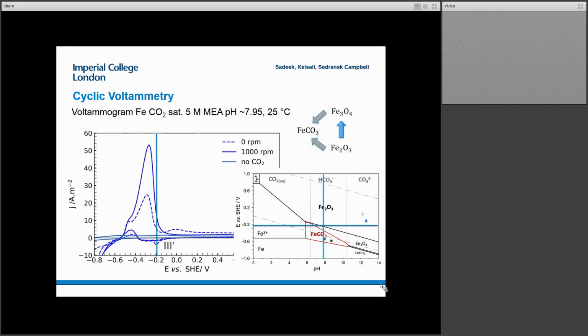but it has perhaps some porosity, we don't know. It may not be as uniform, but what we find on the reverse scan is we see a small but sharper peak, which actually likely is a single reaction. So one of those reactions is returning. And the reason we know that is actually in other experiments where we shift scan rates and temperatures, we're able to elucidate the separation amongst these different mechanisms. So we actually can control, depending on where we sit, which things are going in the reverse direction.